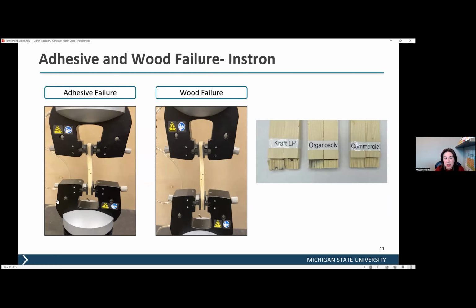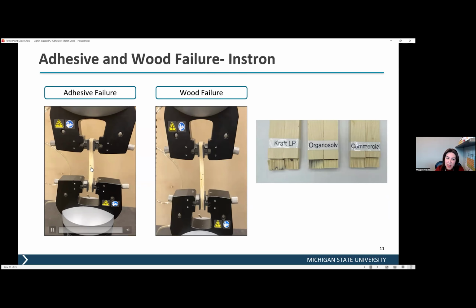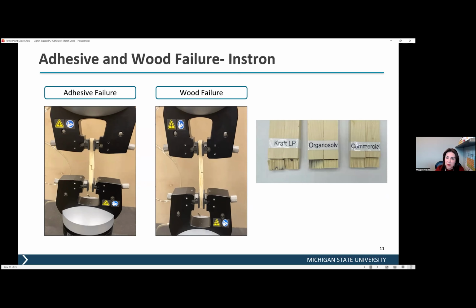You can see the force applied, and when that happens, we call it adhesive failure. This is not the lignin-based adhesive sample, but what we usually like to see is that the force is strong enough to cause the wood to fail rather than the adhesive to fail. And this is the sample.